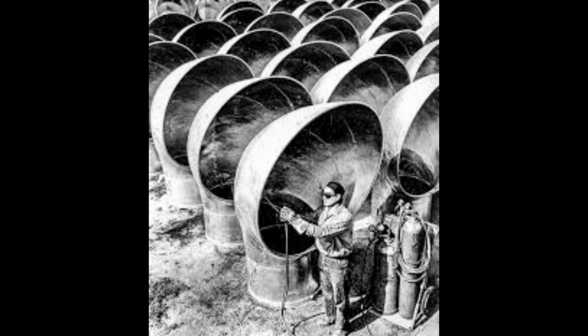To his credit, Kaiser acted immediately. He ordered full-scale tests of Hamill's method, dedicating an entire hull section for controlled reconstruction. The results were shocking. When metallurgists compared conventionally welded panels to those built using Hamill's sequence, the difference was undeniable. Stress gauges showed the old method created internal tensions exceeding 30,000 pounds per square inch at key joints, while Hamill's approach reduced peaks to around 12,000 psi.